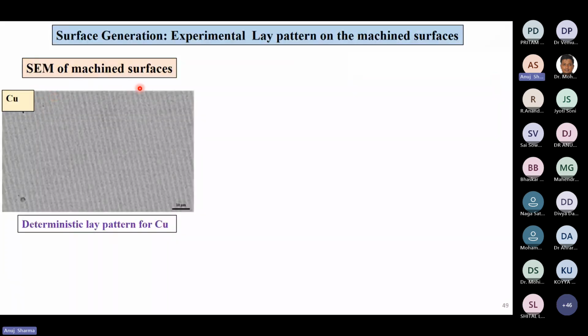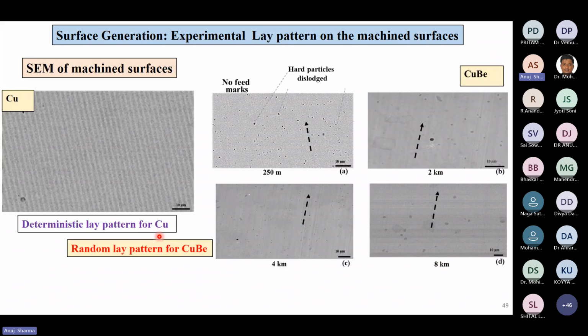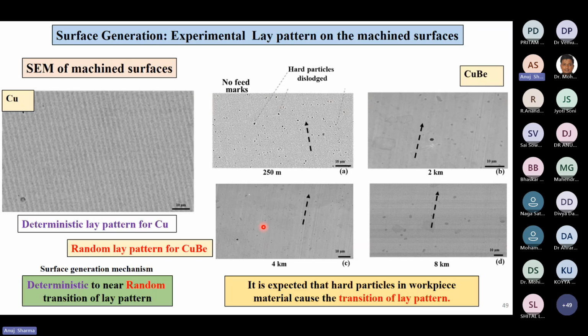By checking the SEM images, it was seen that for copper a well-defined pattern is there. So a deterministic lay pattern was obtained for copper. But in the case of copper beryllium, no visible pattern like copper was seen, although similar parameters were used, and only a flat surface was seen. So it was initially expected that a random lay pattern had been introduced on the copper beryllium surface. It is expected that maybe hard particles have caused this transition of lay pattern.